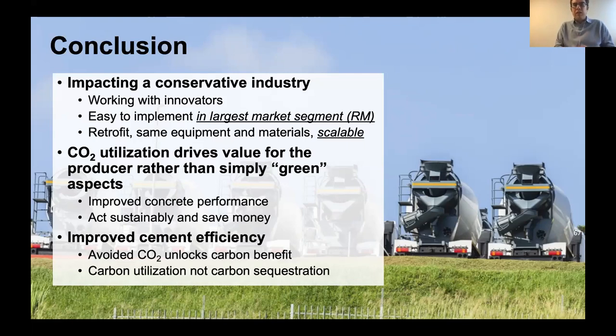If you're adding the CO2 and mineralizing it in the cement paste, you can actually improve the compressive strength, and that allows you to reduce some cement, which is where your carbon benefit comes from. This ultimately demonstrates this carbon utilization pathway. So I'd hesitate to call this carbon sequestration, but it's carbon utilization to make more sustainable concrete.